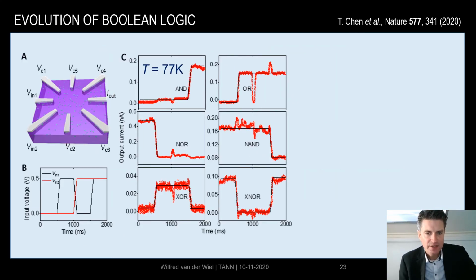Well, first of all, basically as a benchmark test, we repeated more or less the experiments that we also had done on the gold nanoparticle networks, but this time at liquid nitrogen temperature of 77 Kelvin. So the idea is again the same. We have these time-dependent voltage inputs that we apply to two inputs to the device, and we measure the output current. In black, there is the ideal output for the respective gate, and in red, you see the actual output current after the artificial evolution algorithm has been run for typically up to 50 generations. So also here you see that we can realize all Boolean logic at 77K in this case.